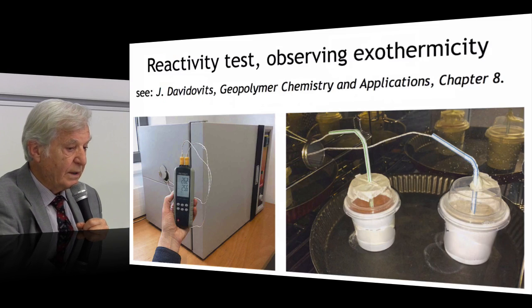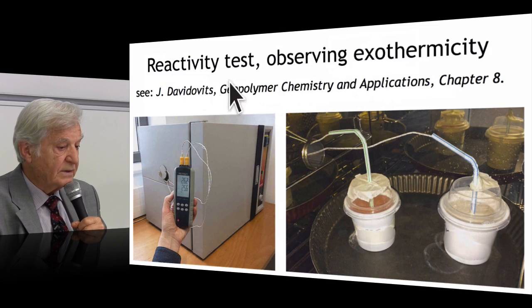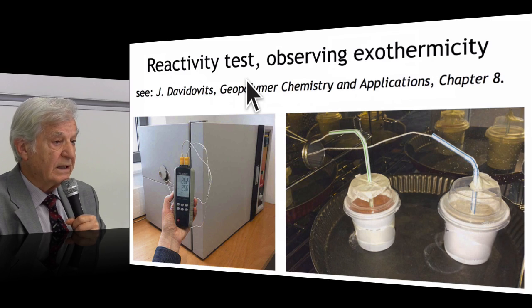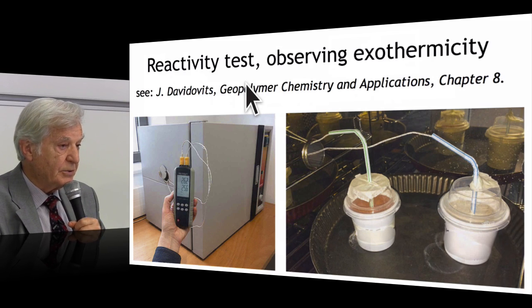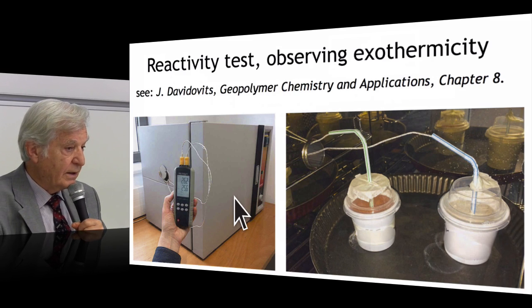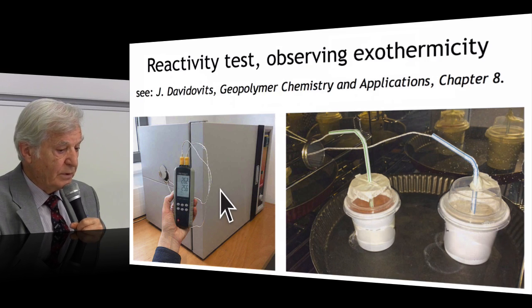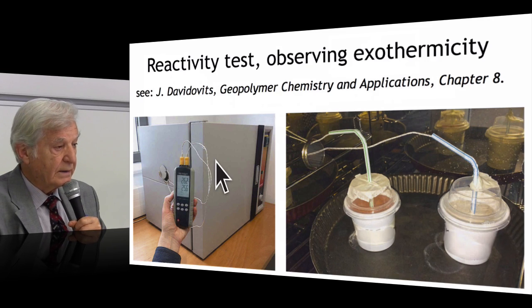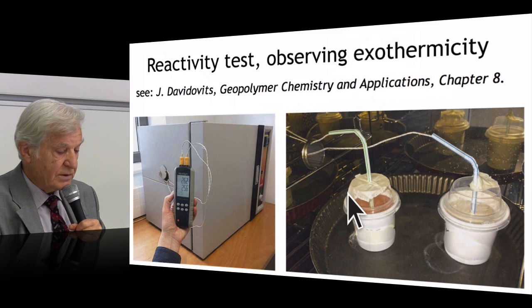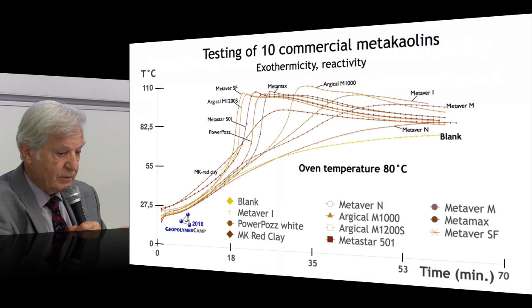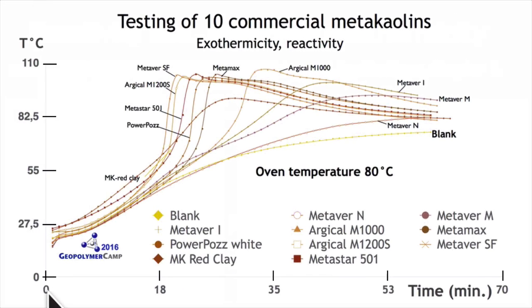And we applied the reactivity test, that is, Metakaolin is exothermic in the alkaline medium, and we are measuring the increase of temperature that we get when we put the sample in an oven at 80 degrees C. So we have here the reference, that is the blank sample, and here it is the sample that will be tested, and this is what we get. We have here the graph, the time, the temperature increase, the oven temperature is 80 degrees C, and we are testing 10 commercial Metakaolins. And you see that they all behave differently.